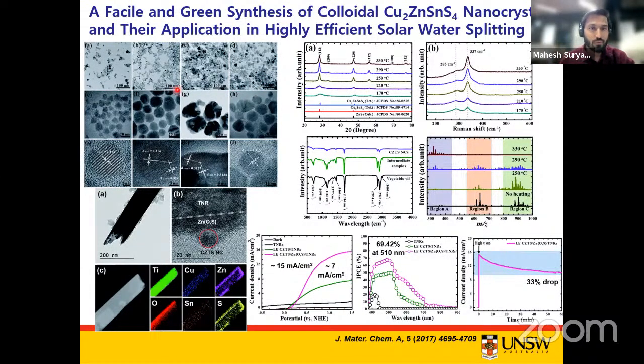So we used vegetable oils to produce CZTS nanocrystals of sizes around 15 to 20 nanometers, and these nanocrystals are synthesized at different reaction temperatures. And you can see that with increasing reaction temperature, there is an increase in the size of the nanocrystals. Of course, I will not go into detail again. Then we carried out different characterizations to further confirm the phase formation, and we found that at all reaction temperatures, there is a formation of CZTS nanocrystals.